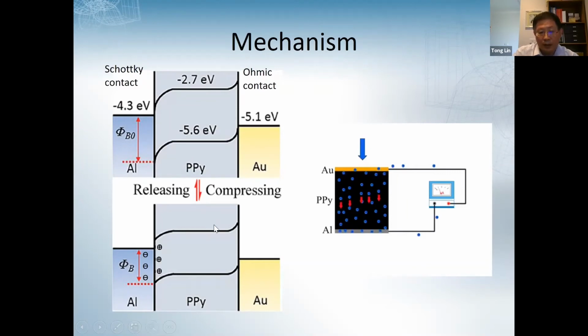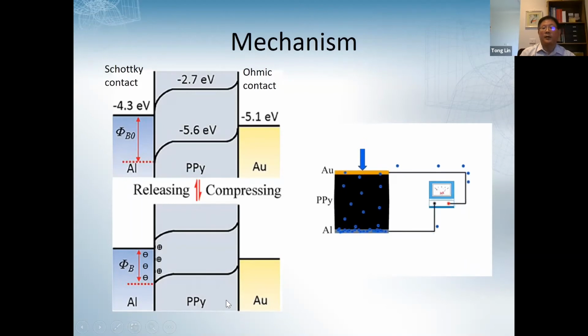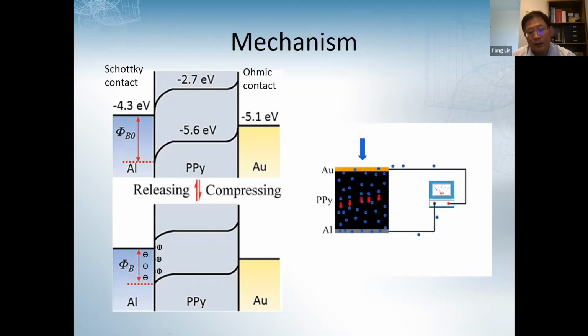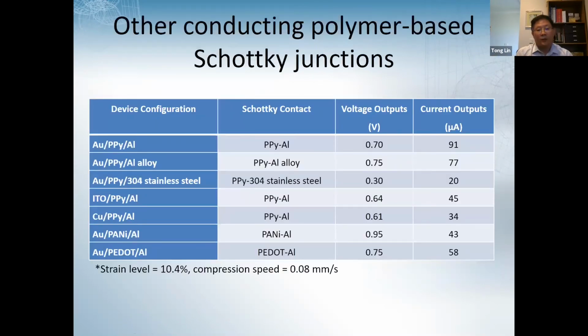So the right cartoon shows the energy conversion process, like this. The electrons are actually pumped from gold through PPy to aluminum, and then return to the device through the external circuit. We also found other conducting polymers, like polyaniline and polythiophene, have similar properties as long as they can form a Schottky junction with metals. So this Schottky junction can generate a DC power under compression, and the voltage output is really dependent on the work function of the materials.